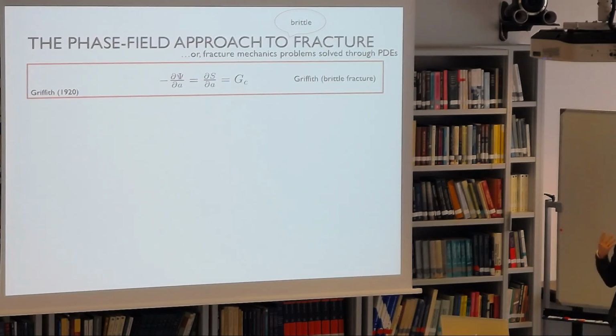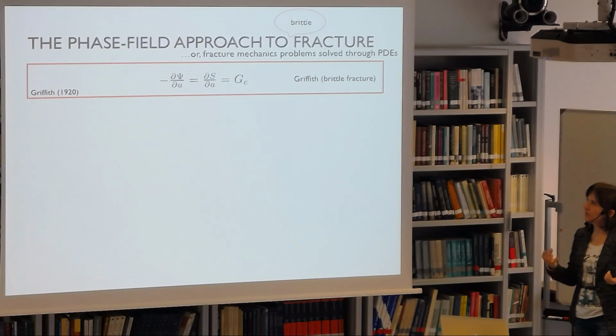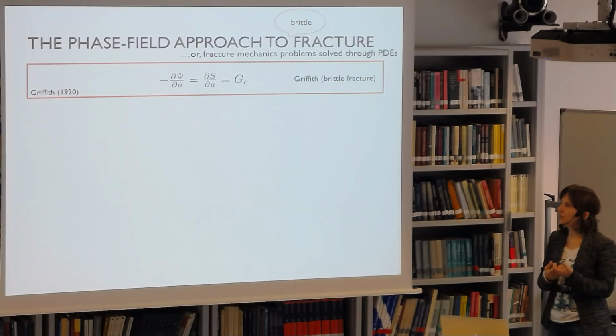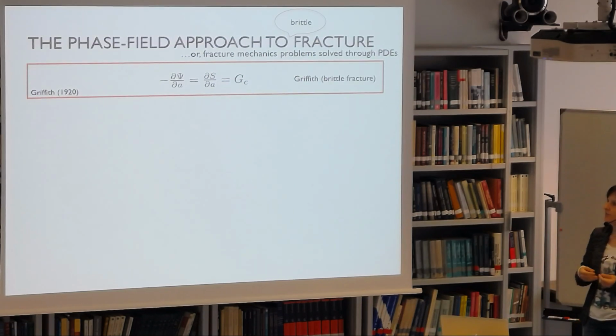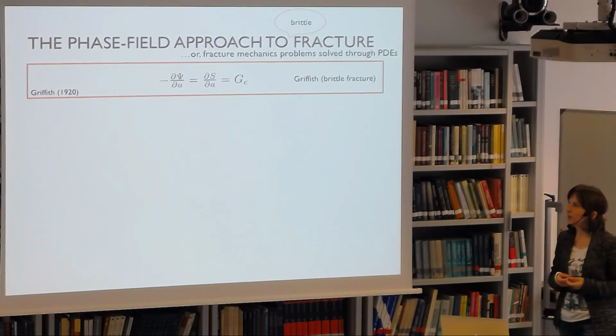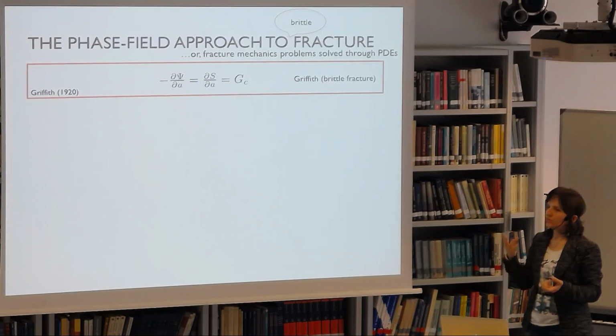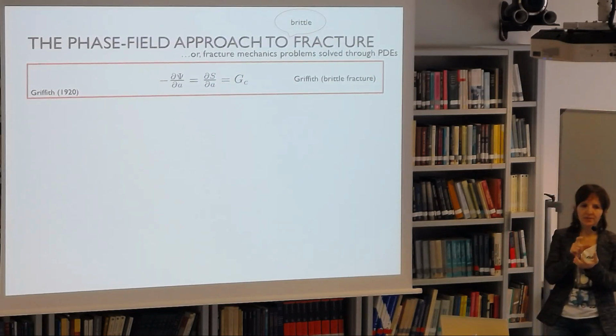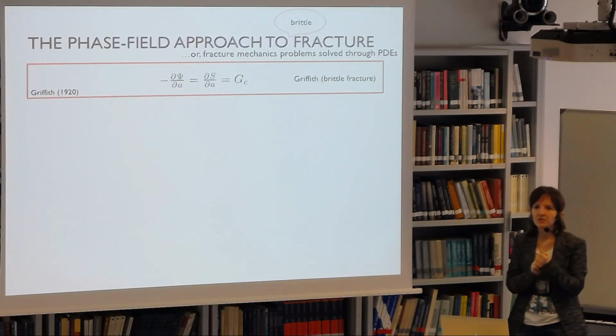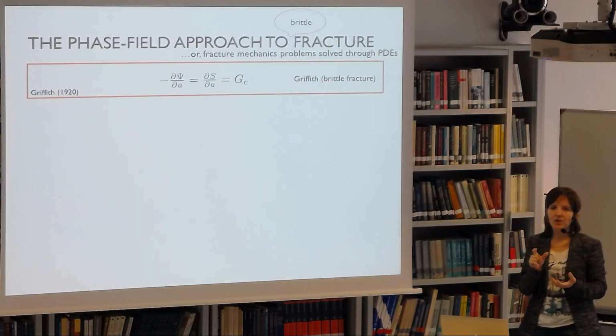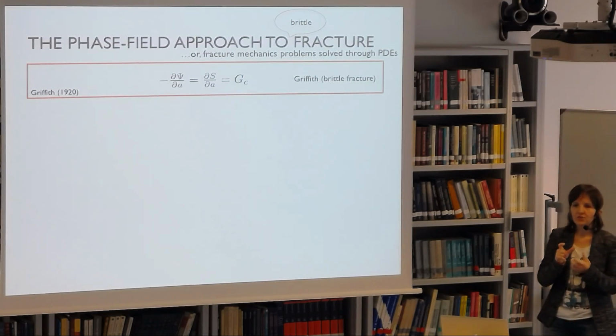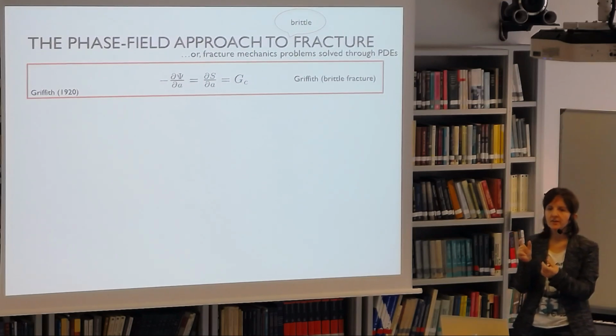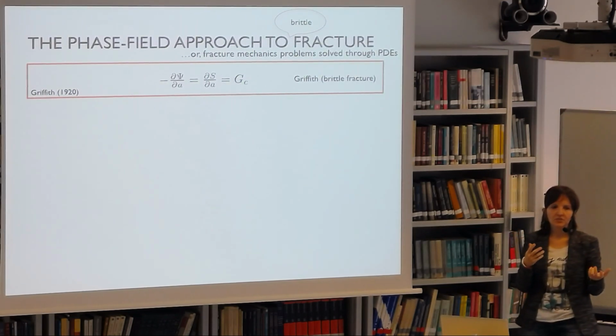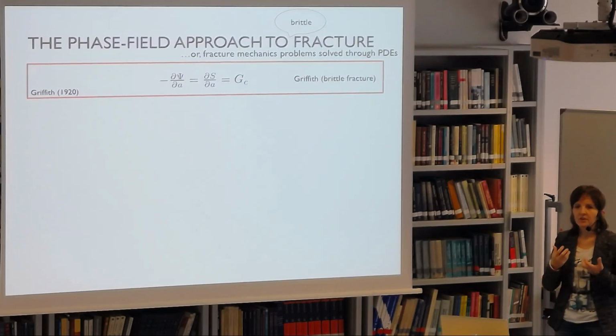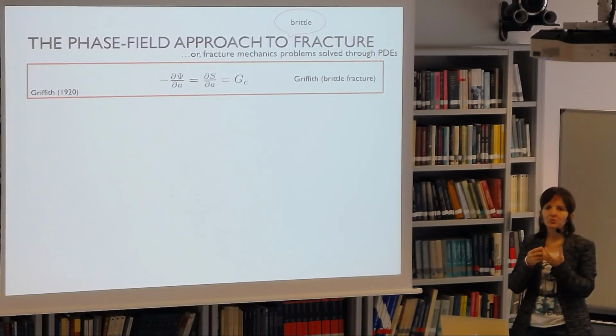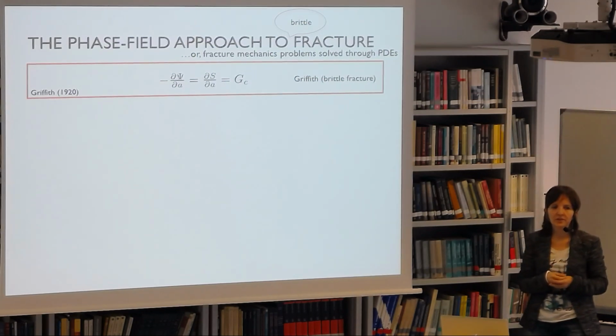So if we go back to the very old approach by Griffith, this is a very simple energy-based approach that we all learn in undergraduate classes. If we call psi the elastic strain energy, then what Griffith is postulating is that we already have a pre-existing defect or pre-existing crack in the structure, and the initial length of this crack is called A. Now, if the crack propagates by an amount dA, on one side there will be a release of elastic energy, and on the other side there will be the need for a supply of additional energy to create the additional surface dA of the propagating crack.